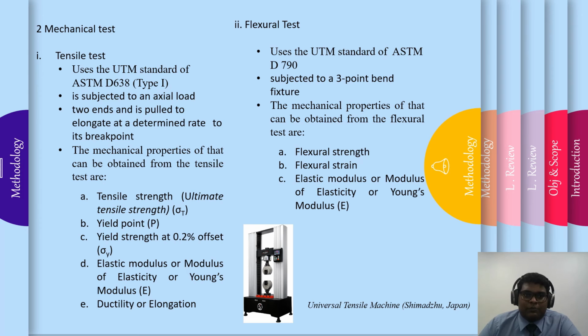After preparing the test specimens, the specimens must undergo the mechanical tests. The mechanical tests are conducted using a Universal Tensile Machine (UTM), Shimadzu, Japan. The mechanical tests are divided into two: tensile test and flexural test. The tensile test is a destructive method in which specimens of a standard shape and dimension are prepared according to ASTM D638 Type 1. The specimen is subjected to a tensile load. During the test, a dog-bone shaped specimen is gripped at its two ends and is pulled to elongate at a determined rate until its breakpoint.